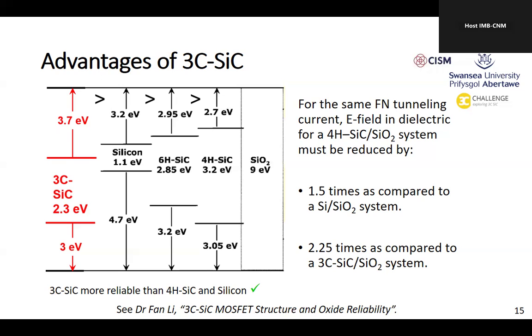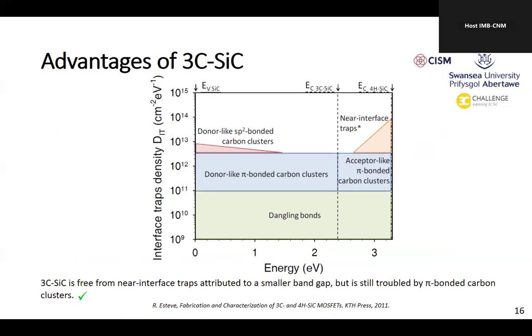So this project was about creating boules based on seed sublimation, and proper wafers in cubic silicon carbide, and it worked quite well. I'll show some results from that in a second. But basically, going back to this diagram, you can have a much larger electric field in the oxide on cubic silicon carbide before you get current injection into the semiconductor, gate leakage basically. And that will be at much higher temperatures, because of this large band offset.